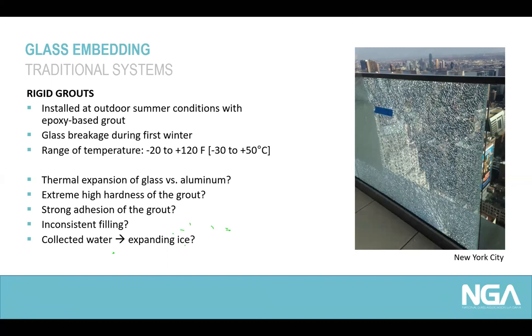Epoxy-based two-component systems can have a quick cure, especially in hot summer conditions. It could be difficult to fill the base shoe consistently. An inconsistent filling again could apply concentrated stress to the glass, and inconsistent filling leaving some cavities in the base shoe could also be a risk of collecting water, and that water can attack the interlayer, and frozen water expanding in the system can even cause glass breakage.